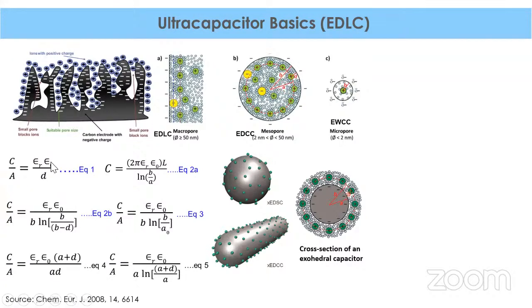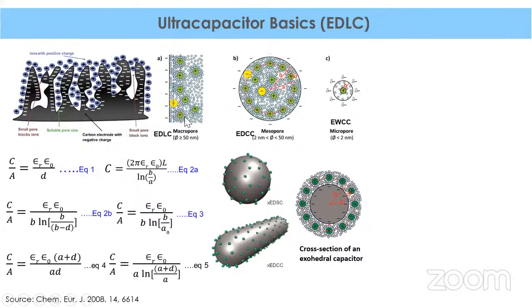What they suggested is that the simplification of the carbon electrolyte interface to an EDLC does not consider the curvature of each pore. Accordingly, the close interaction between pore walls is neglected in the simple parallel plate capacitor model. There are different kinds of pores. You can see here, there are three types of pores in porous carbons: macropores, mesopores, and micropores. Macropores generally have a diameter of more than 50 nanometers, mesopores are more than 2 nanometers but less than 50 nanometers, and micropores are pores of less than 2 nanometers diameter.